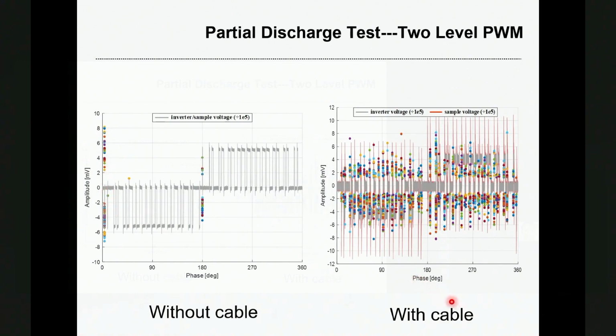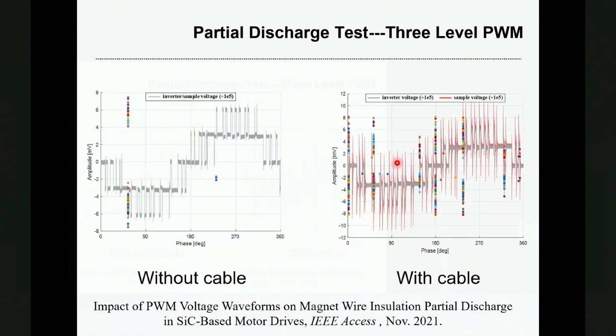And if there is a cable between the inverter and the twisted pair, then there will be over voltage at the twisted pair. And as you can see, there will be more PD events almost at every switching transition. So we have also tested that for three-level converter. Again, the PD events occur during the polarity change. And if you have a higher voltage, then you will get more PD events.